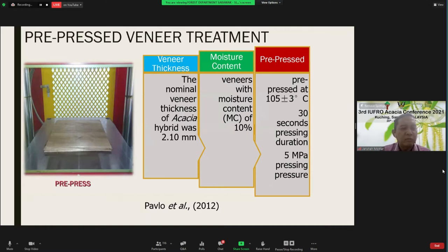Thus, Pavlo 2012 suggested 105 ± 3 °C for 30 seconds and at 5 MPa would increase the mechanical strength of the LVL panel most eventually. Next.